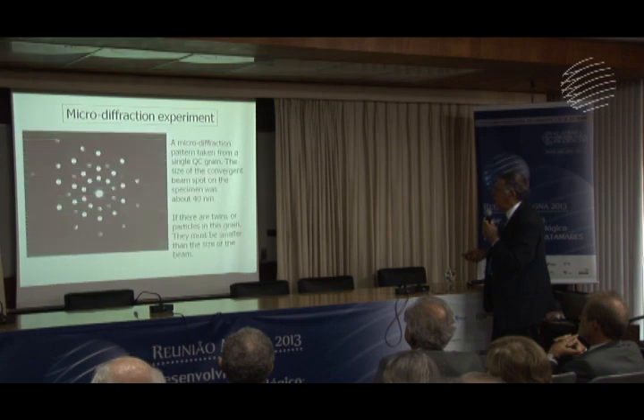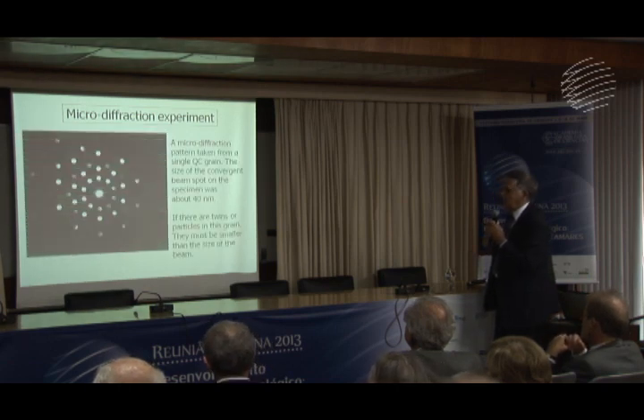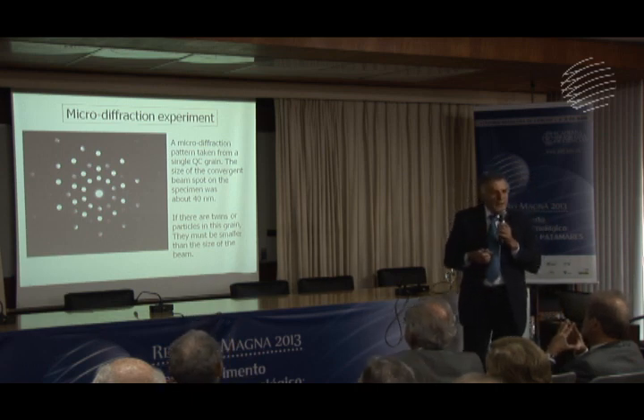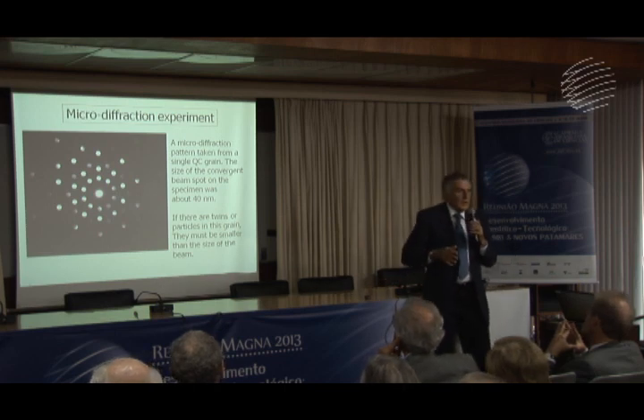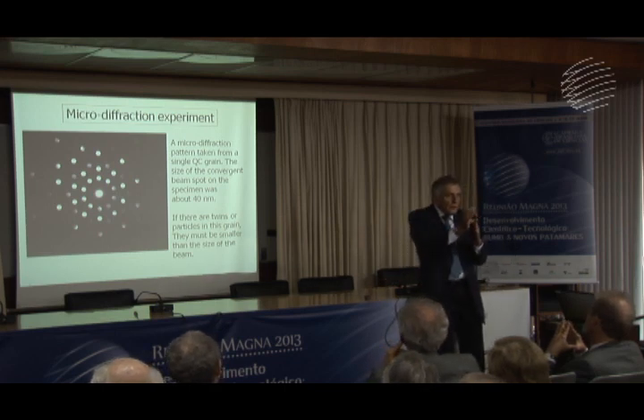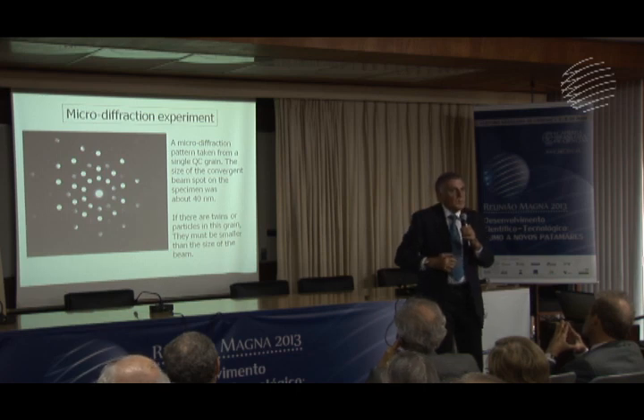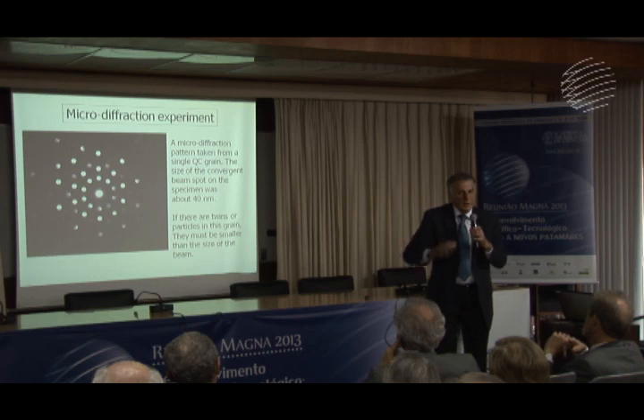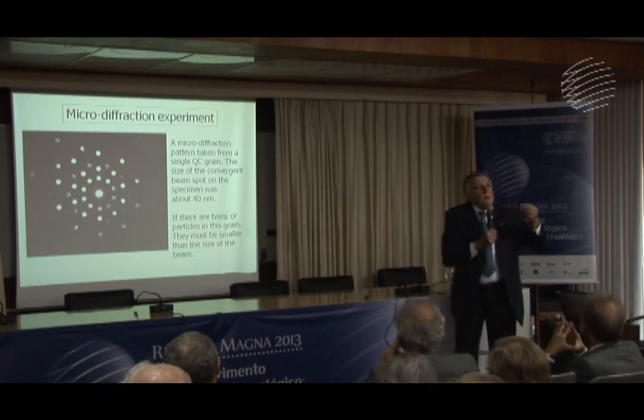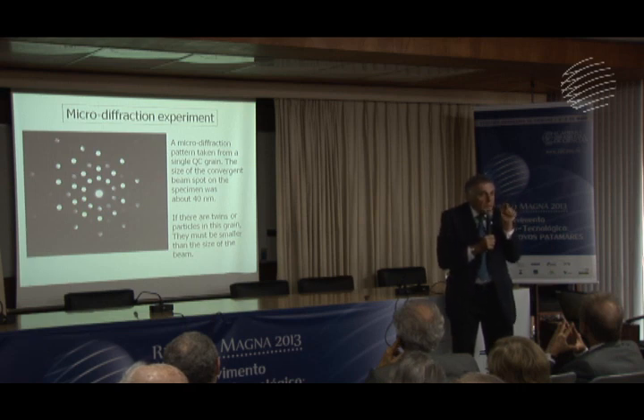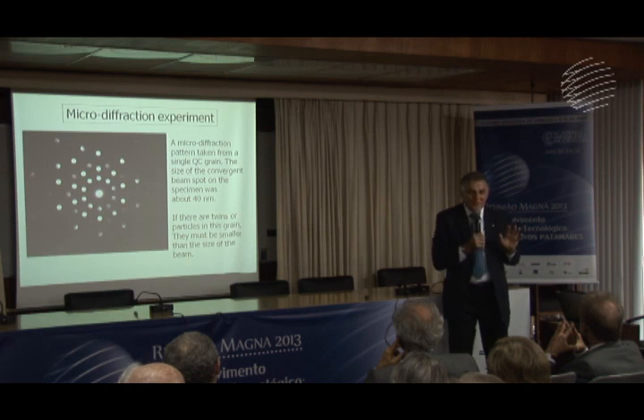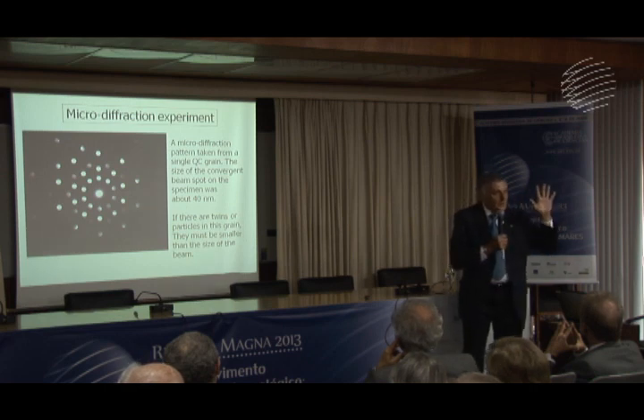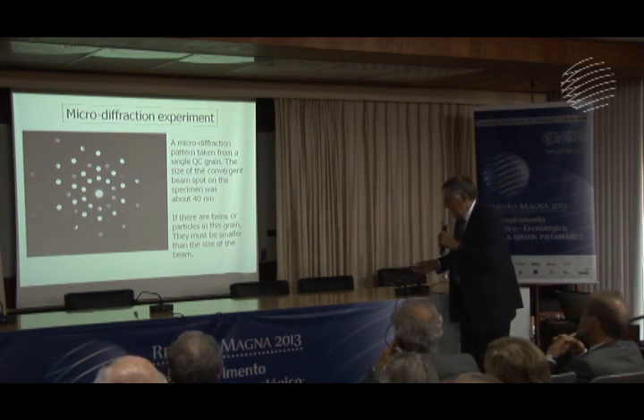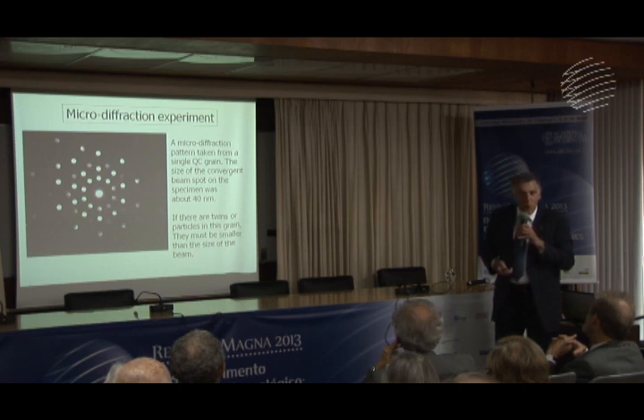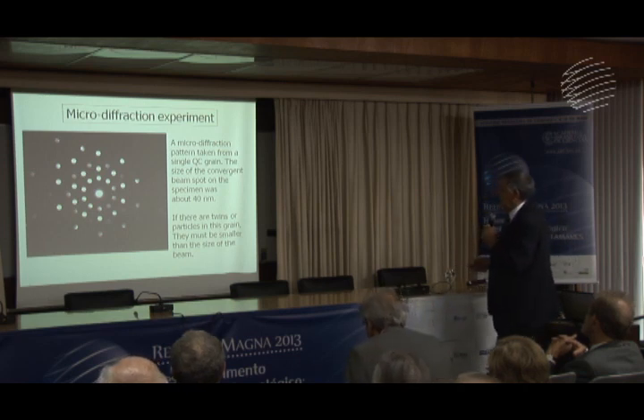And I did another experiment. This is called microdiffraction, or CBED, convergent beam electron diffraction. What you do with convergent beam electron diffraction is the following. You take the electron beam and you converge it onto a very, very small spot, as small as you can. And on that microscope, that spot was about 400 angstroms, 40 nanometers. It was an old Philips, excellent Philips microscope. And this was the size of the spot. And I said, okay, if the twins are very, very small, then with a small beam, I will hit one of them. And if I hit one, I'll see a periodic diffraction pattern. Never happened. Everywhere I went, this was the diffraction pattern. Always five-fold. So I understood that the symmetry is a property of the material rather than defects in the material.